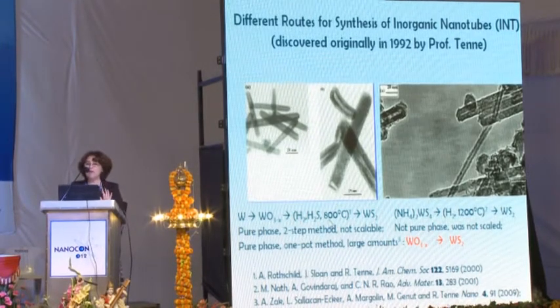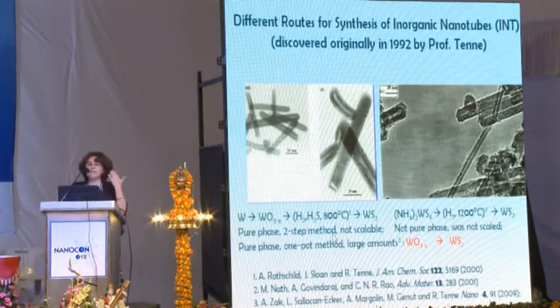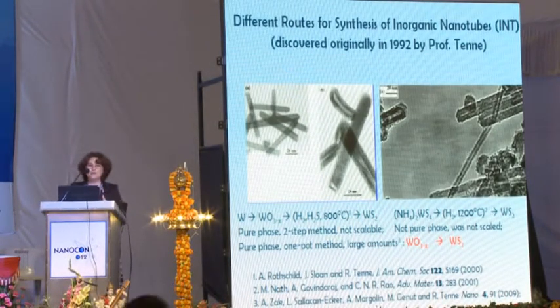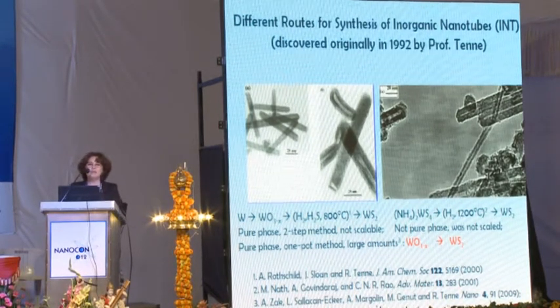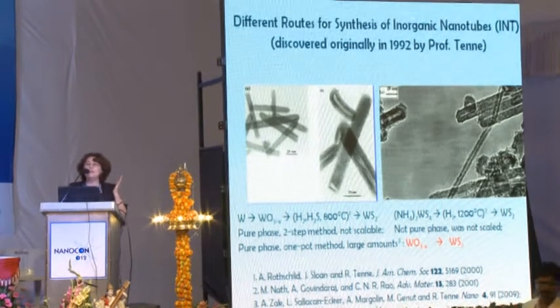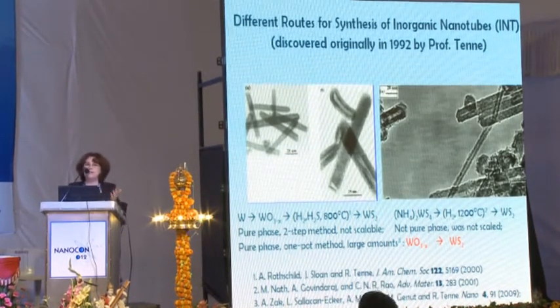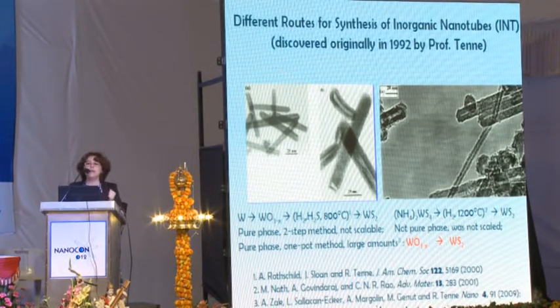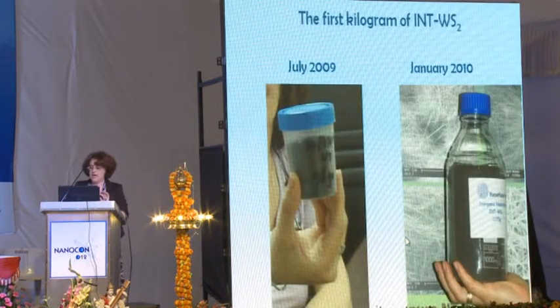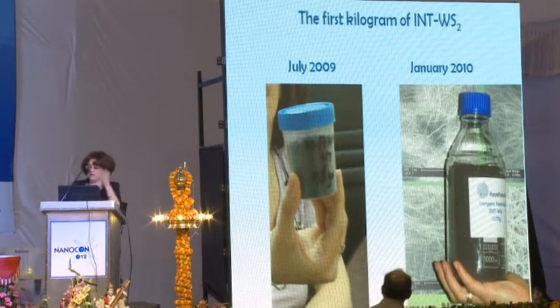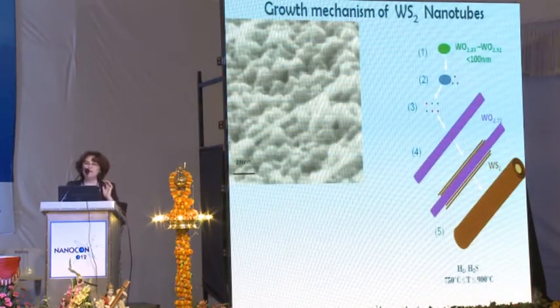I will show you now the production. This work inspired me to try to synthesize these nanotubes in big amounts, which I will show you in a few minutes. Today we can produce up to 100 grams, or half a kilogram, or a kilogram per week of inorganic nanotubes, pure phase. This process is based on a precursor material, tungsten suboxide. You can see here the picture of the first kilogram and then a bottle. I will go through a few details of the synthesis.